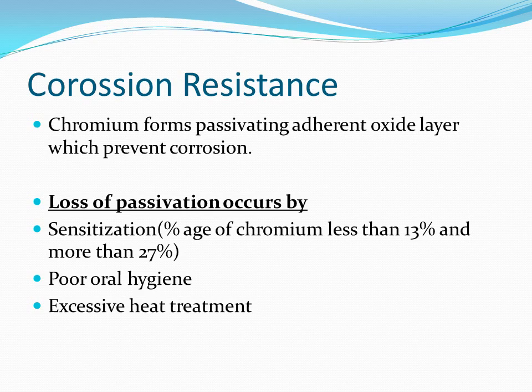to various factors. For example, if the percentage of chromium is less than 13 or more than 27%, this can lead to sensitization. If the patient has poor oral hygiene and there are heavy calculus deposits, this can lead to the loss of passivation, and also excessive heat treatment can lead to the loss of passivation or sensitization.